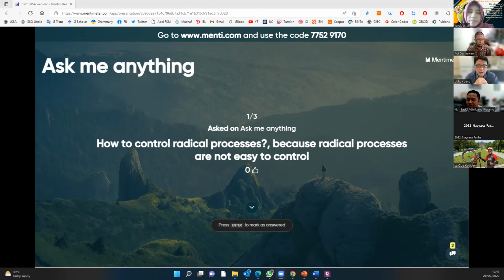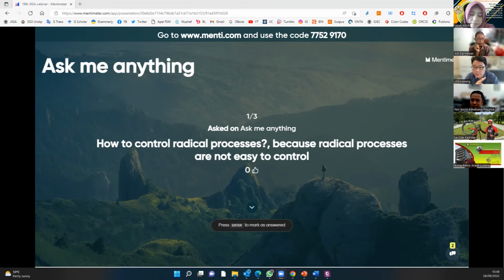So actually, my postdoc advisor, Krzysztof Matyjaszewski, who invented ATRP, they study a lot about how to control the polymerization better. And learning from him, my understanding is during this process, you actually have two factors that are very important. One is the radical concentration, because with low radical concentration, you can slow down the termination. The second is rapid exchange. So the PDI, you can see in my case, I can make the molecular weight increase linearly with the conversion, but PDI is broad. We think it's because of the kinetics. The thermodynamics give you low radical concentration, but the kinetics give you low dispersity. Means you need to make the radical exchange very fast.